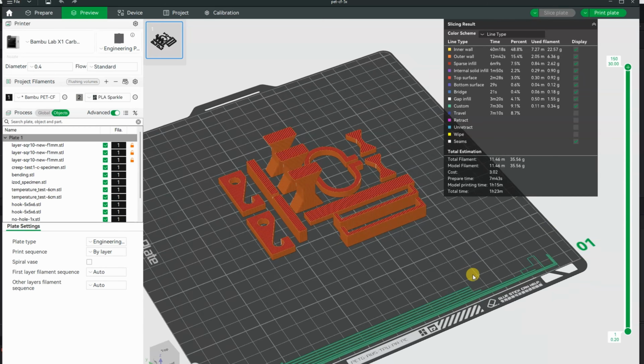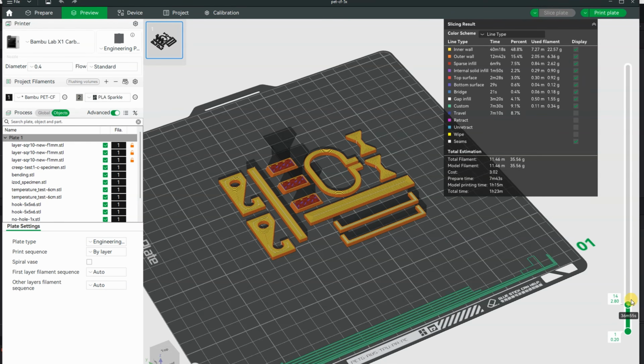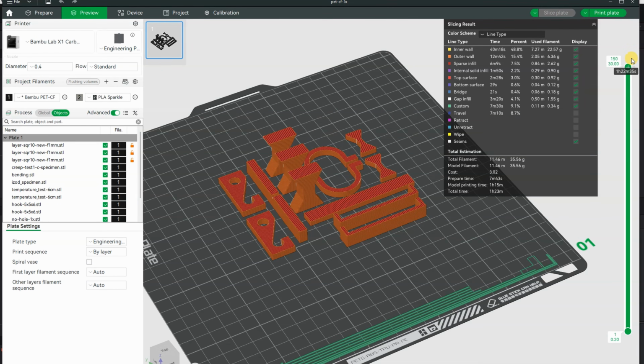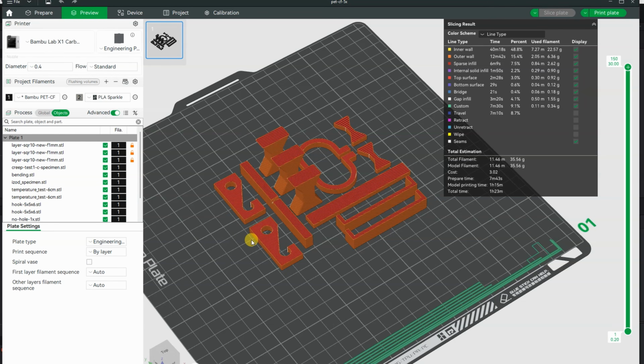These are the test objects from this video. For the layer adhesion test, I will have these printed with 2 walls and 20% gyroid infill. Smallest cross-section area is 10 by 10 mm. All other test objects are solid inside, printed with the maximal number of walls. I will have these 2 hooks, one of them will be annealed.